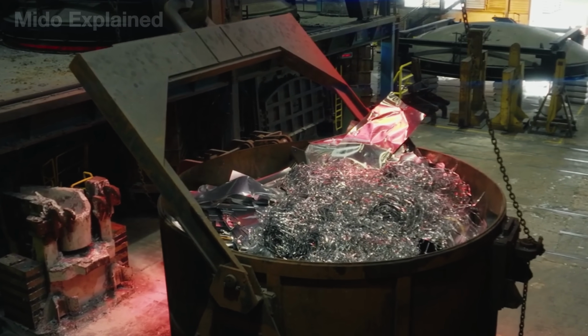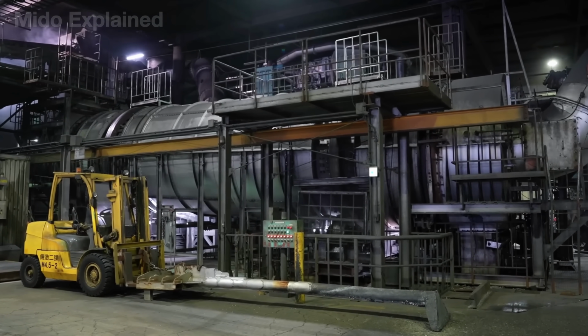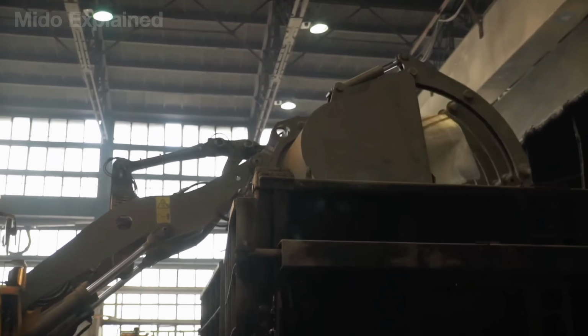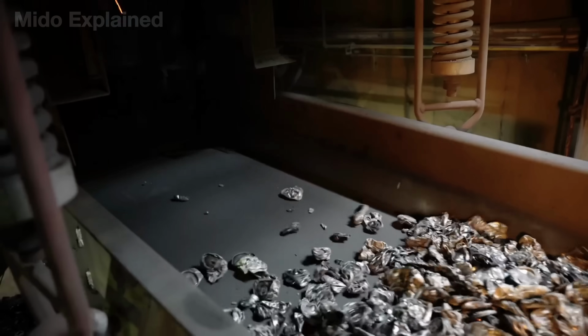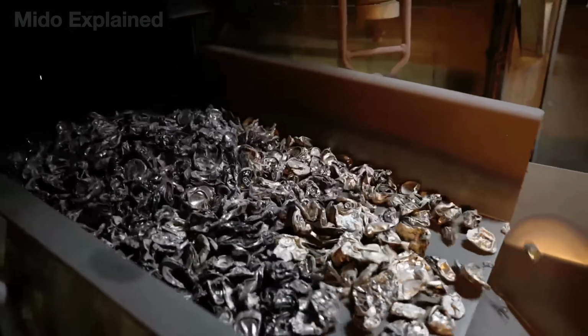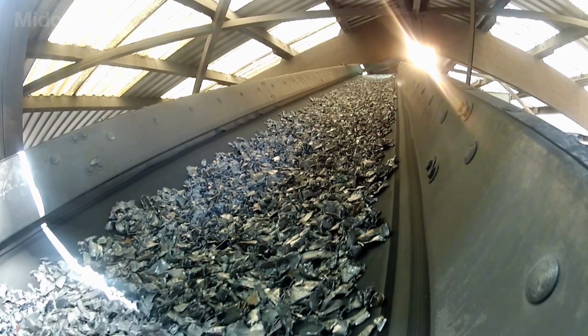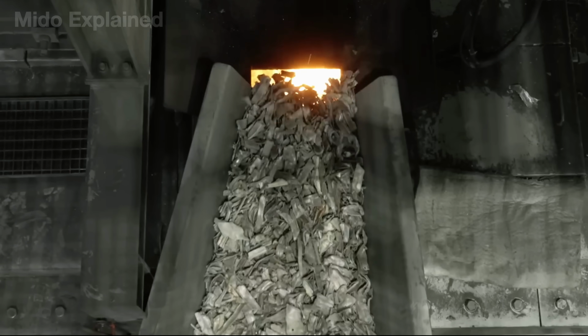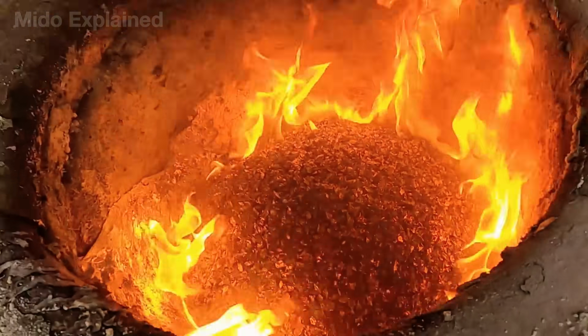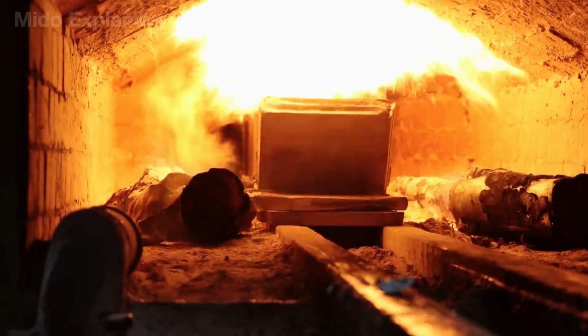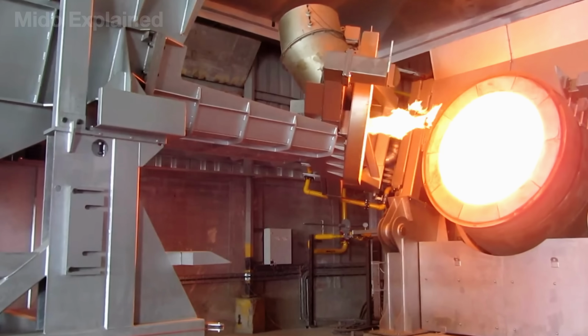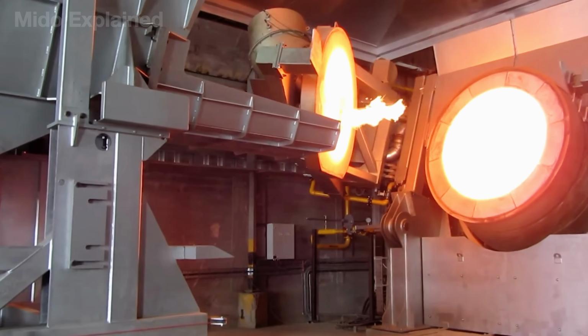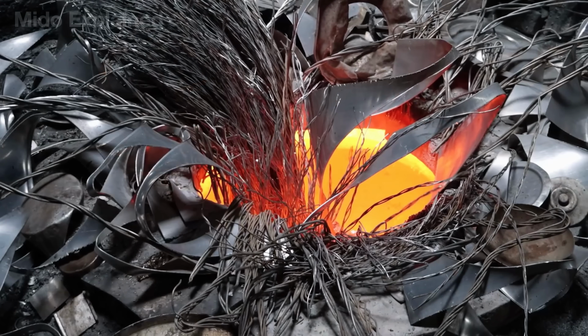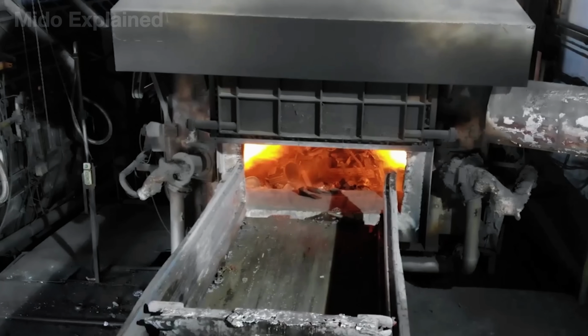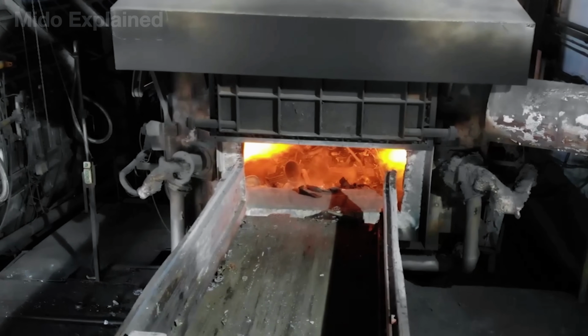Before being melted, the aluminum pieces pass through a decoating furnace to remove any remaining paint, ink, and coatings, minimizing impurities and fumes generated during the smelting process. Then, the aluminum is fed into industrial melting furnaces, where the temperature is raised to approximately 1,400 degrees Fahrenheit. At this temperature, the solid aluminum pieces gradually transform into a bright silver liquid metal in a short period of time. Depending on the scale of production, a modern furnace can hold from 50 to over 100 tons of molten aluminum in a single batch.